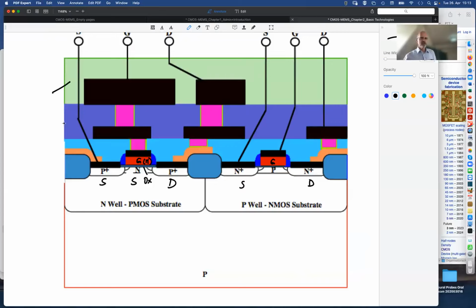These are insulating materials. So insulators. This one too. So silicon oxides, sometimes doped silicon oxide, and maybe on top of silicon nitride. These are PECVD deposited or thermally oxidized materials, which insulate well, which insulate the metallic layers from each other. But of course, you need to go from one layer to the other at certain places, and this is symbolized by these pinkish structures that are the so-called vias. So this is called a via. It's the semiconductor jargon for interconnection through oxide layers, through insulators. It's a via.